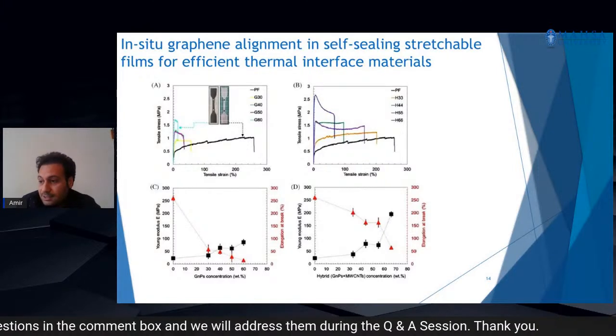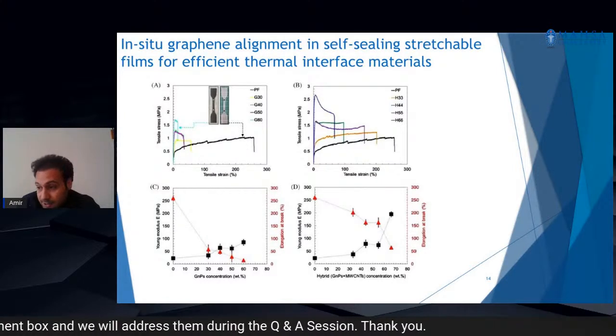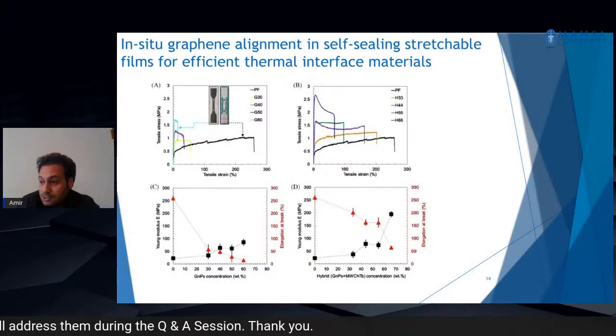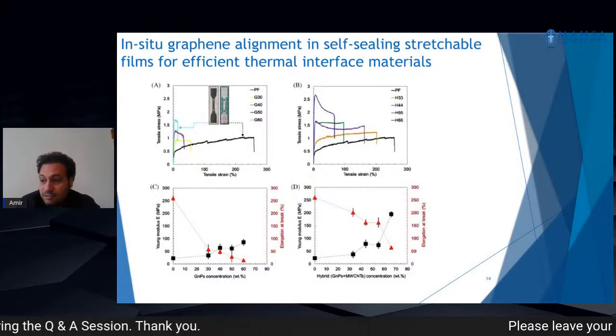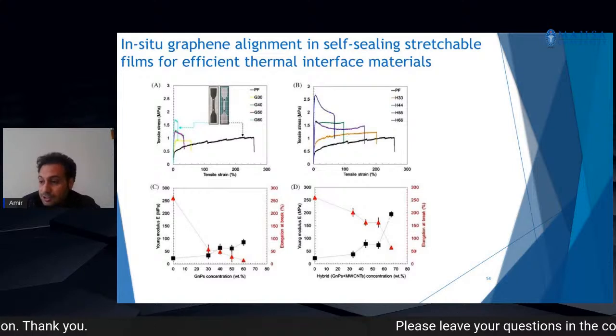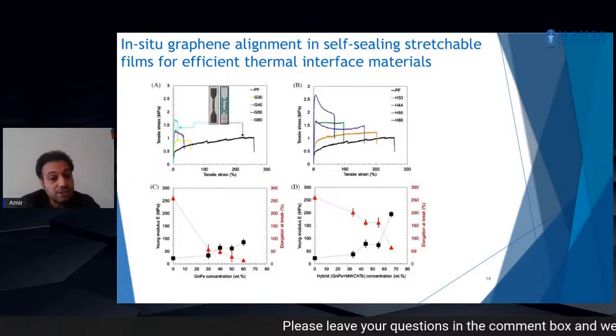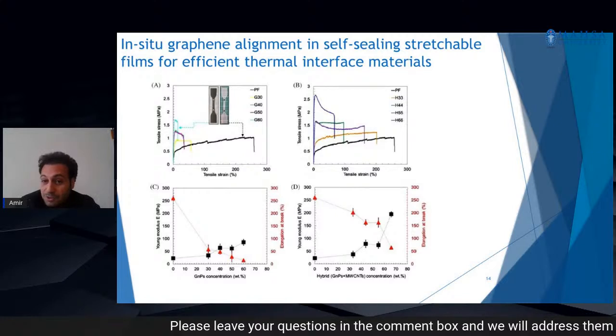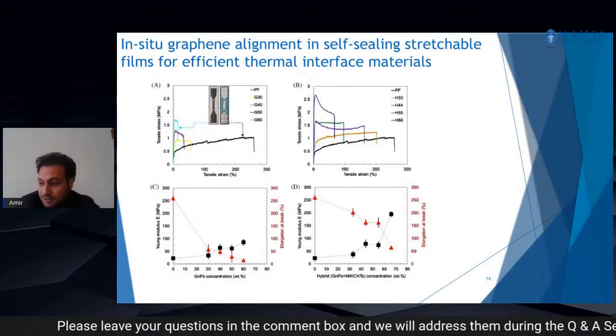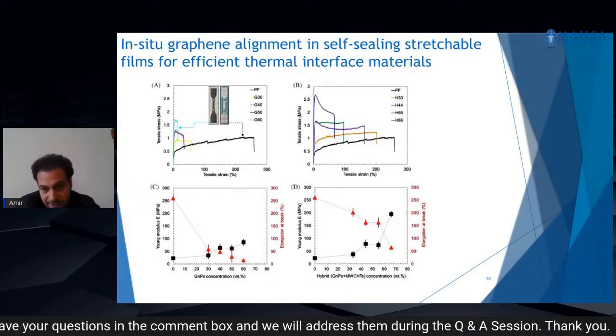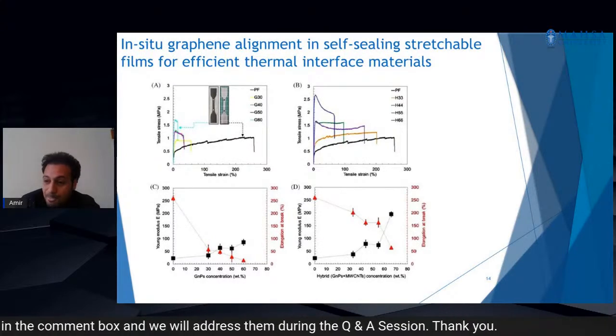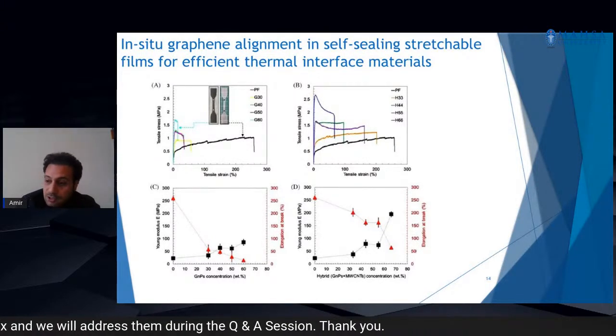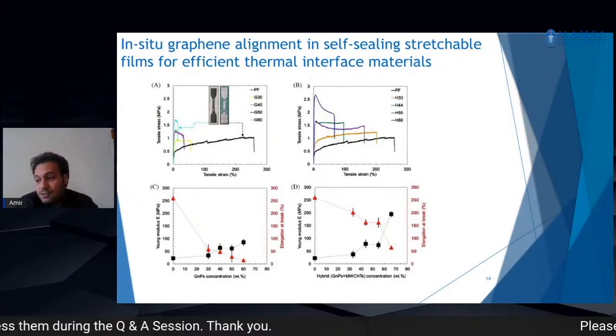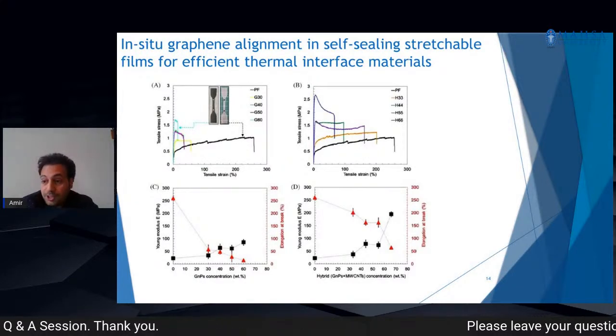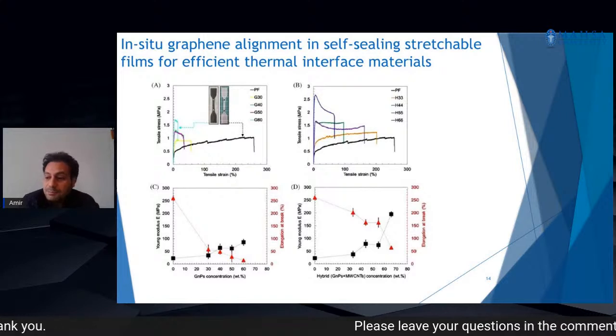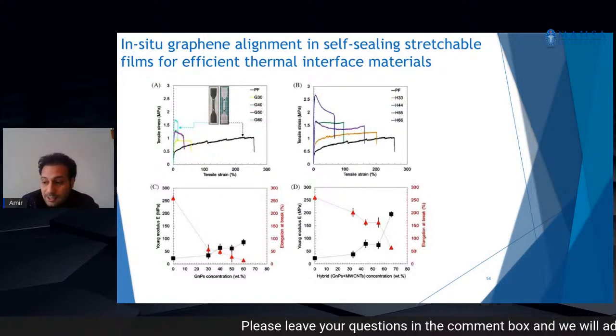However, adding the MWCNTs in these nanocomposites resulted in a significant recovery in the hybrid elongation at break value, which was measured to be 200 percentage. In fact, adding the MWCNTs improves the mechanical properties of the GnP-filled PF nanocomposite by improving elongation at break values and ductility.